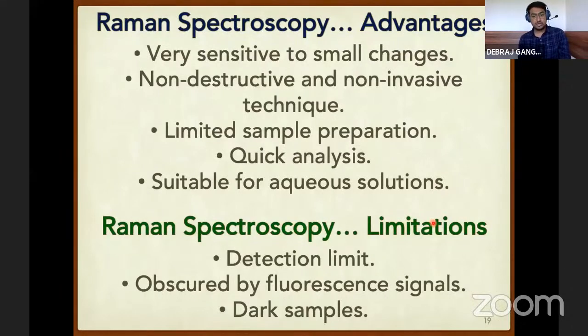But there are some limitations of Raman spectroscopy. One is the detection limit. For very small concentrations, Raman spectroscopy fails because it is a very insensitive technique, and we have to use a very high intensity of incident radiation, that is laser. Even then, we have very few Raman scattered photons, because only 1 in a million photons will get Raman scattered, which is very hard to detect. We need very strong detectors for getting the Raman spectra. So the detection limit of Raman is very low.